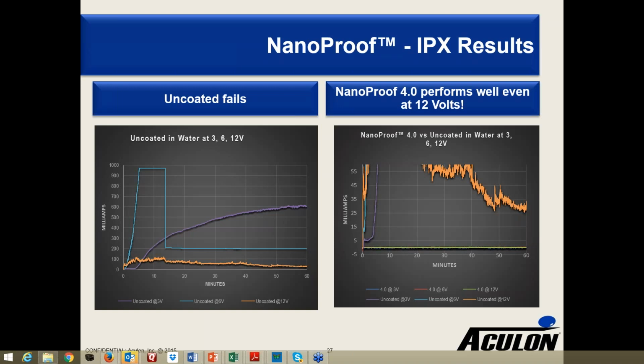You can see uncoated, obviously, in water. There's a pretty quick current spike, and it's dead. And in all cases, with an uncoated piece, what you'll end up getting is immediate shorting out, and you'll also get, in some cases, corrosion, and then it'll actually become insulating from all the copper oxide that's built up. But all of these, when you take them out of the bath, they're completely destroyed. They're just blue or white or black oxide all over the place.